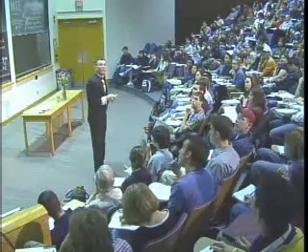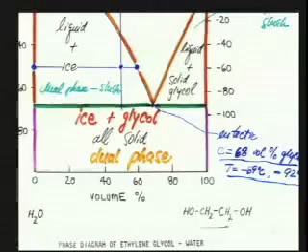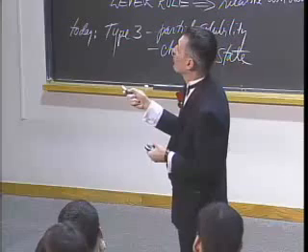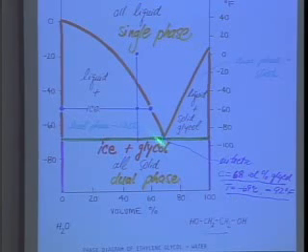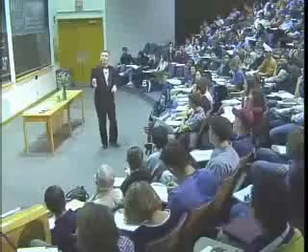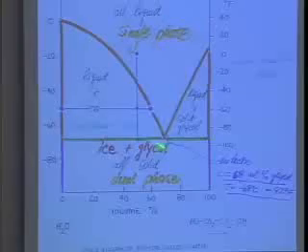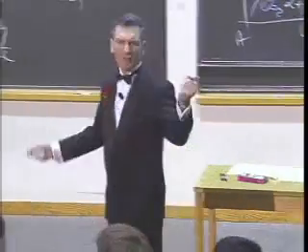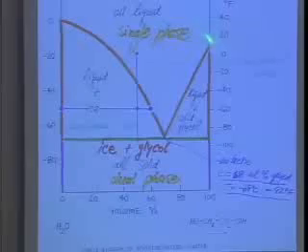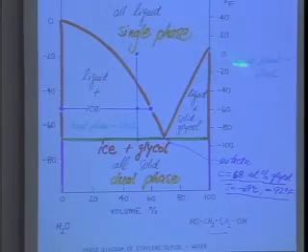of most driving needs. Now, if you want, you can get maximum freezing point protection by adding about 2/3. In other words, 68 volume percent glycol gives you a eutectic at minus 69 degrees Celsius or minus 92 degrees Fahrenheit. That ought to take care of everybody in this room. I don't know anybody here that's driving when it's more than minus 92 Fahrenheit. So that should be okay. But if you want to be an enthusiast and decide, I'm not a cheapskate, I'm going to use pure ethylene glycol. Why dilute it with water? Well, pure ethylene glycol freezes at about, here it is, and this is the Fahrenheit scale here.